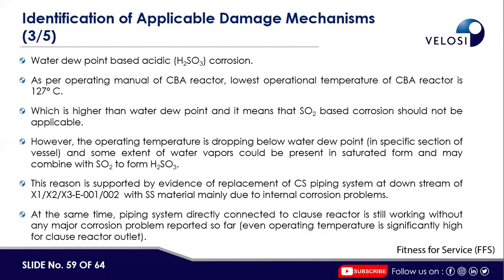This reasoning is supported by the replacement of the CS piping system at the downstream of these reactors with SS material, mainly due to internal corrosion problems. At the same time, the piping system directly connected to the reactor outlet is still working without any major corrosion problem so far, even though the operating temperature is significantly higher at the reactor outlet.